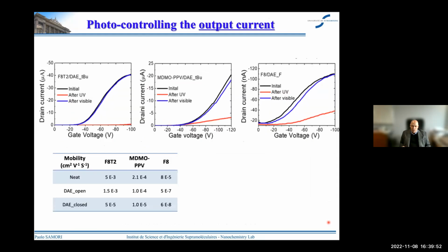And what I'm going to show you in this slide is how, for the three different types of blend, we can trap and detrap the hole transport. We can start from the neat polymer, and then we blend with diarylethene, we lower a bit the field effect mobility, which actually, when we bring the diarylethene to the closed state, decreases drastically, but this is highly reversible. So we have an on-off ratio of the output current triggered by light that exceeds 500.